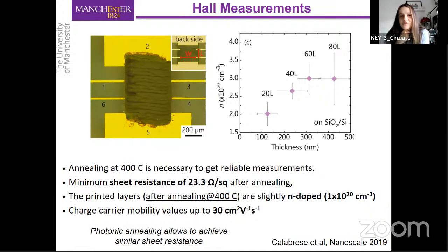However, from the Hall measurements, it turned out that the printed graphene film, even after such a harsh annealing, is actually still slightly doped. Which was kind of surprising, and we think that this is due to eventually some pyrene residual that is trapped in the film. We don't think that is coming from the water. Typically, water will p-dope graphene, and in any case, the doping, if you look at the charge concentration, is actually very small.